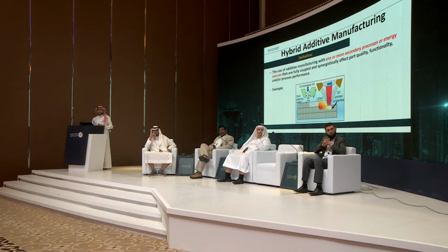So what we mean by hybrid additive manufacturing or directed energy deposition, as you can see on the screen, is you have powder coming out from coaxial nozzles, 4 coaxial nozzles or 3 coaxial nozzles, and then you have a high power laser. It can go up to 2 kilowatts. Coming onto the metal, it can melt, deposit, and print the powder being deposited at the same time. So the term hybrid additive manufacturing comes from the fact that you use one or more secondary processes or energy sources with 3D printing.